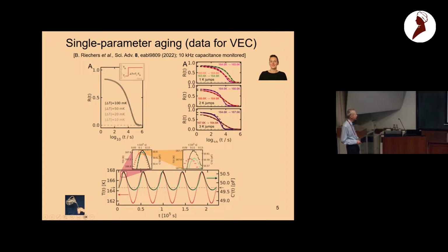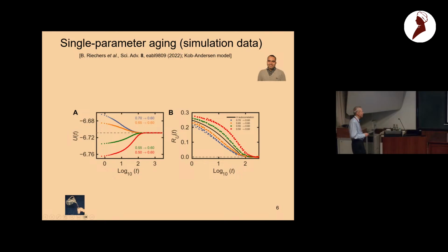In the same paper, we also tried to see whether we could confirm single parameter aging in computer simulations, using the standard Kob-Andersen binary Lennard-Jones model. This was done by Saeed, at the time a PhD student of ours from Iran. Here we consider jumps to a relatively high temperature, 0.6. Nowadays we do them to lower temperatures. The quantity that we study is the potential energy. You need a lot of simulations to get good statistics because it's just one number, a global quantity.